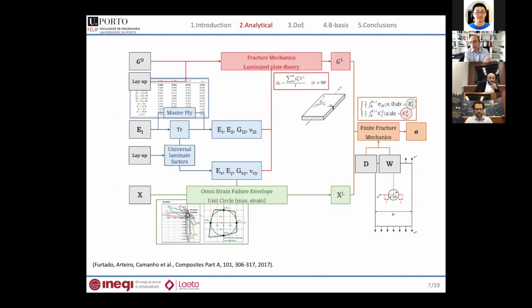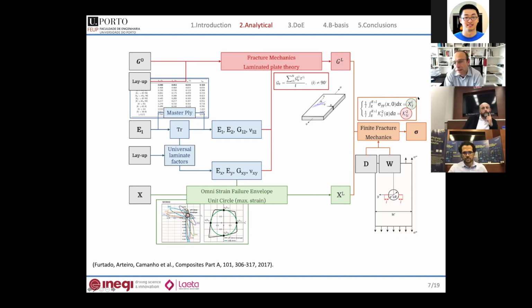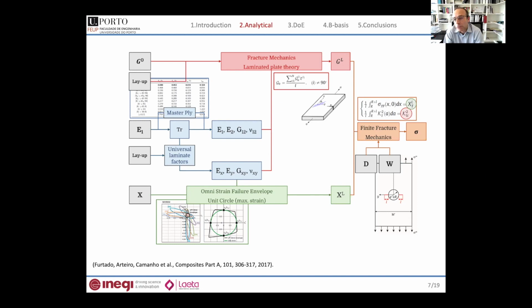Then we need to understand what are the parameters that we're going to use to define the sampling process. And coming back to the finite fracture mechanics equations that you can see here, we have, of course, the geometry, the hole diameter and the specimen width that are used on the left-hand side of these equations. And we have two material properties. We have the notched strength of the laminate, and we have the fracture toughness of the laminate. And of course, this changes every time we change the layup, okay?